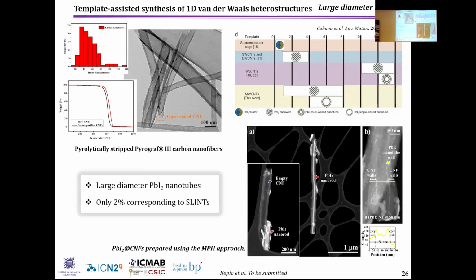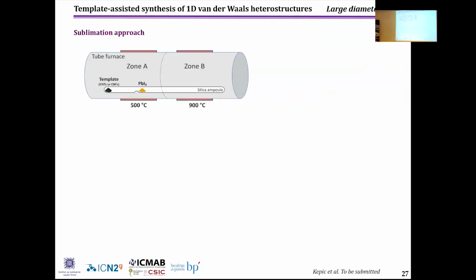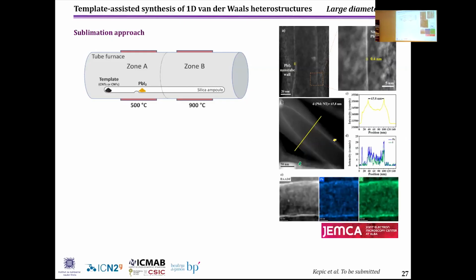However, only 2% of these corresponded to single layer nanotubes. So we switched to another approach. So we employed a sublimation approach in order to increase this ratio, to increase the amount of inorganic nanotubes that are created inside the fibers. So in this case, we also were able, with the sublimation approach, taking advantage of the formation of the gas in the reactor, in the silica ampoule, to prepare these nanostructures.